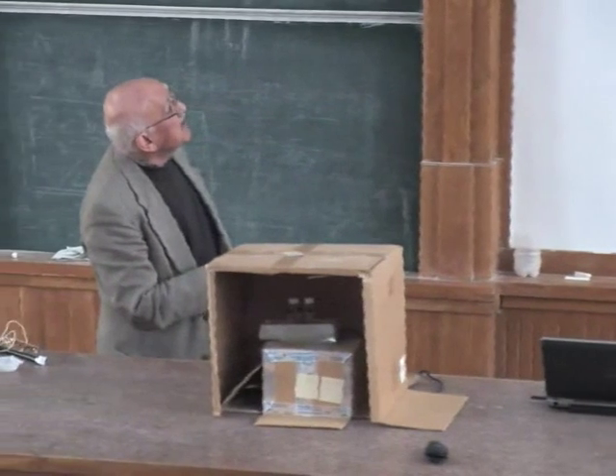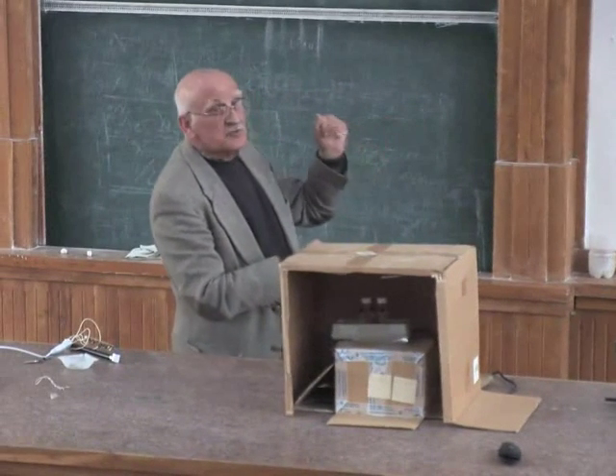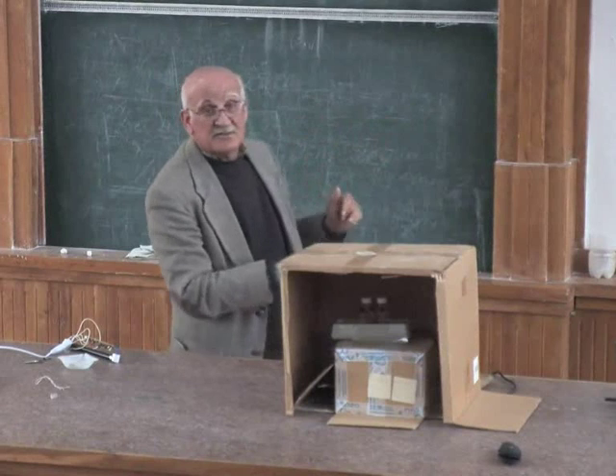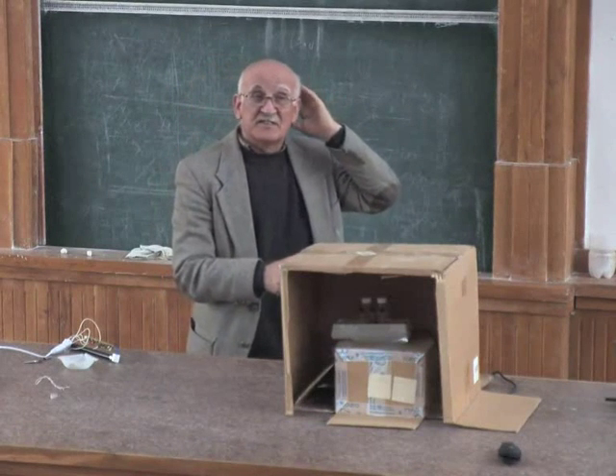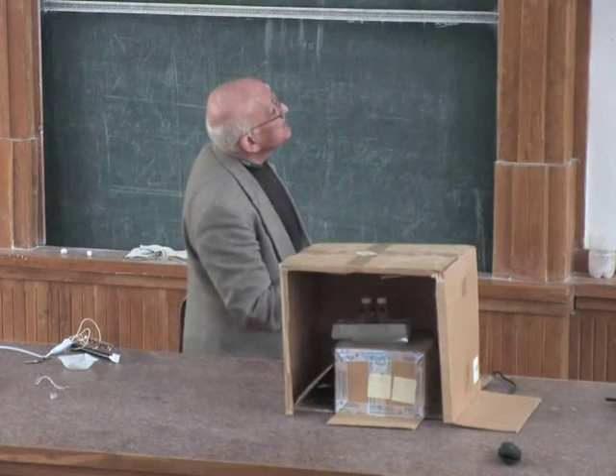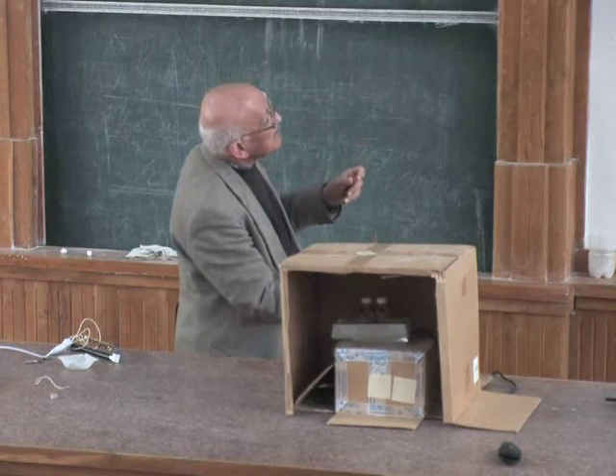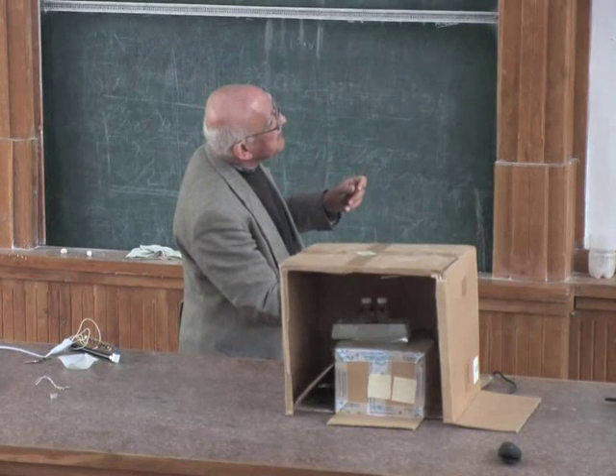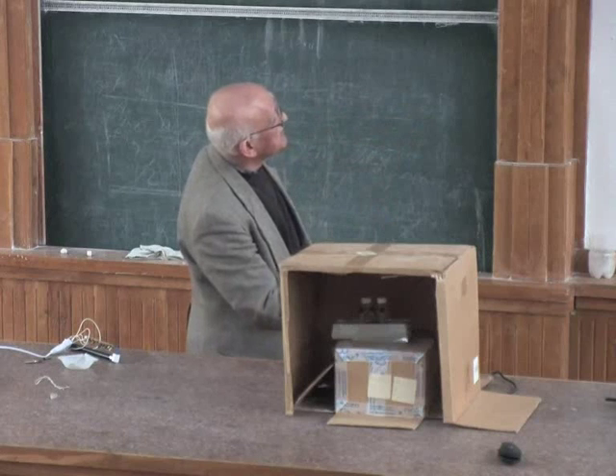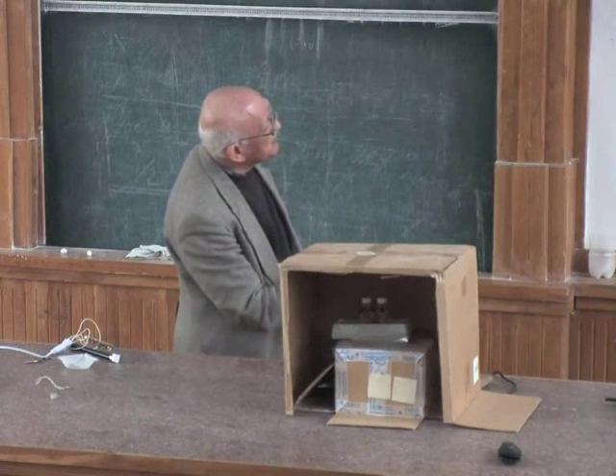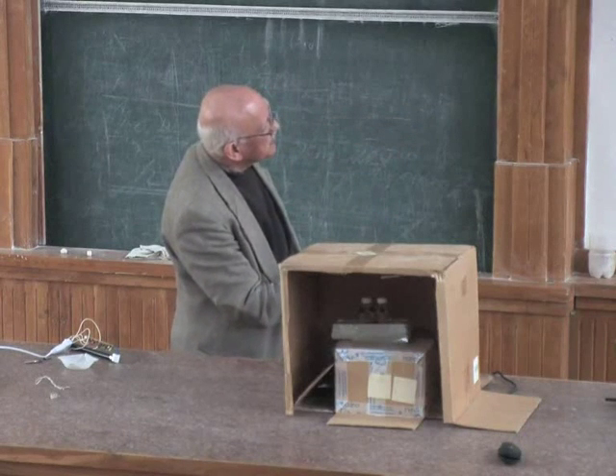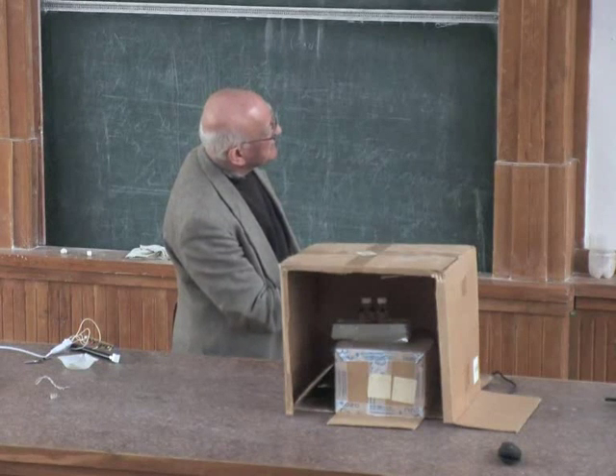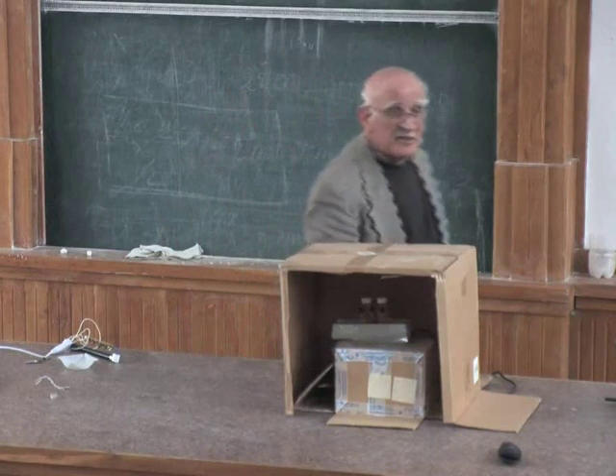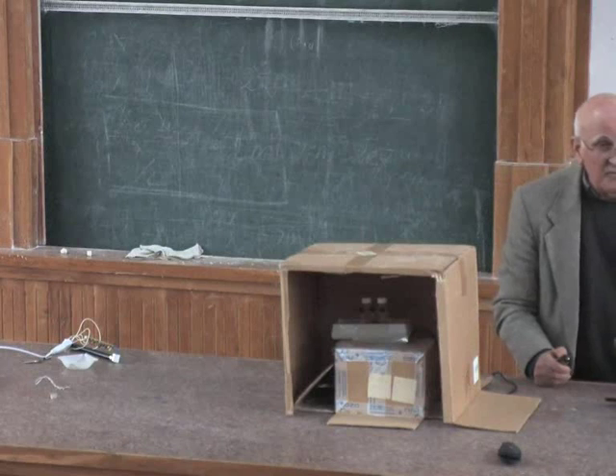Here we try to push the nanoparticles with electric and magnetic fields. This is important for astrophysics, nanodust. The same nozzle comes in, then we intersect it with the electric and magnetic field and push them. Here is the magnetic field, and we were able to use a quadrupole magnetic field to focus the nanoparticles on a disk with a hole in the middle. How much time do I have? Five minutes? Yes.